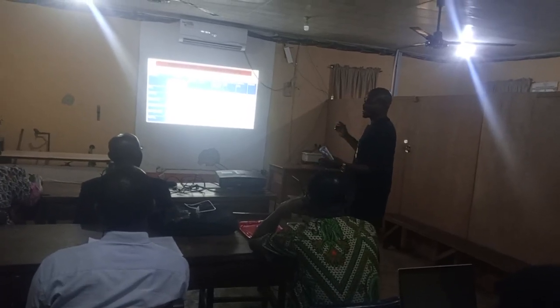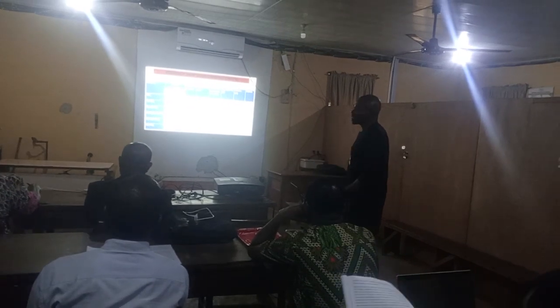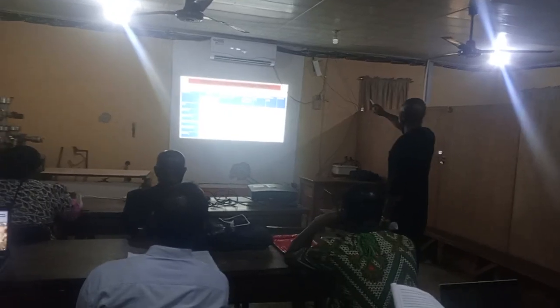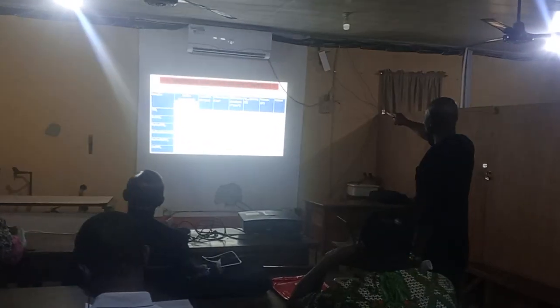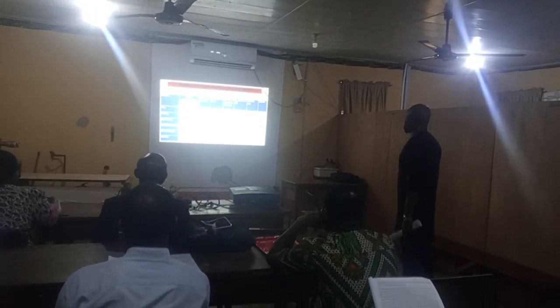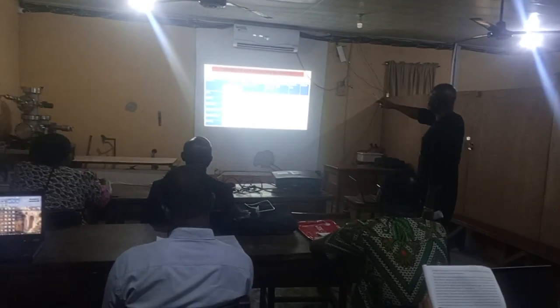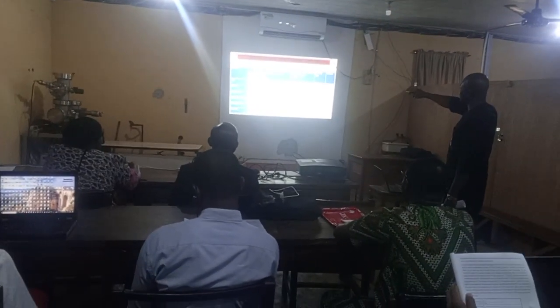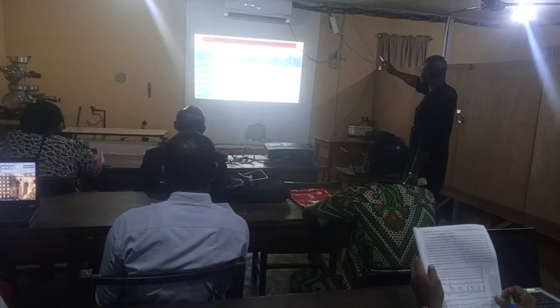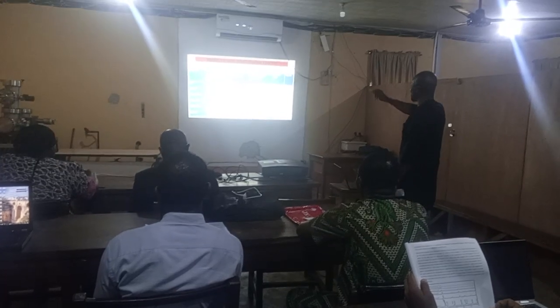A larger diameter than the titanium ion. Then we also discovered the broadness of the full width at half maximum. The broadness of the full width at half maximum also supported our claim that this material is a polycrystalline material. Then we discovered that the crystallite size actually decreases, which was also the reason for the increase in the microstrain and dislocation density.